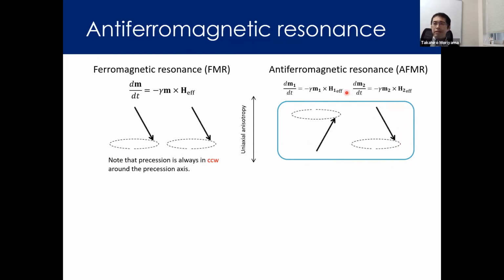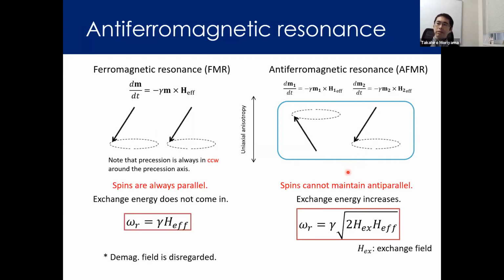So this basically increases the system energy by the exchange energy, because the antiferromagnet prefers the antiferromagnetic coupling, okay? But it cannot maintain that during the precession. So this is why the exchange field term comes into the antiferromagnetic resonance like this.